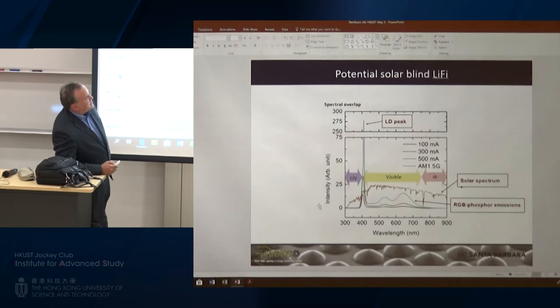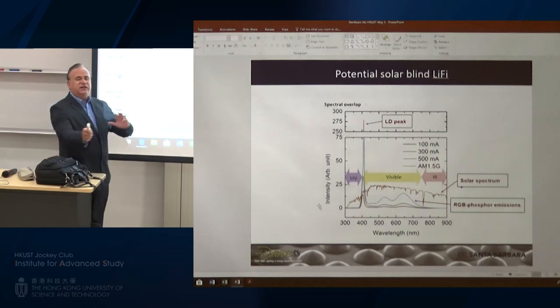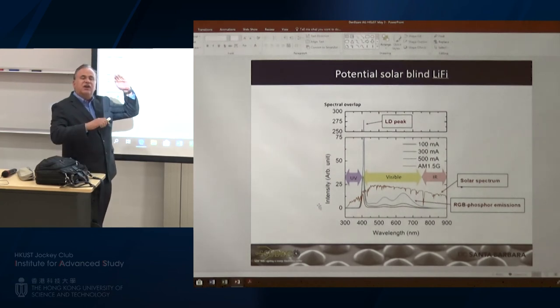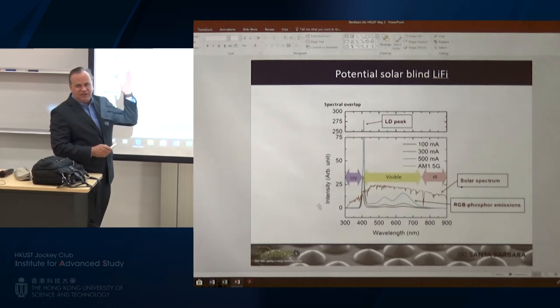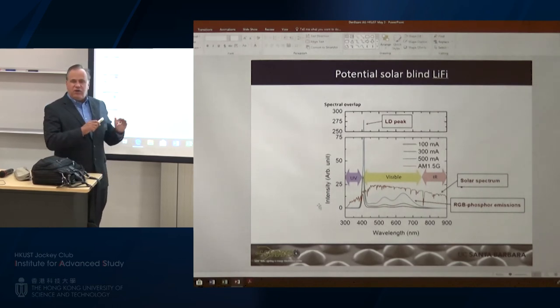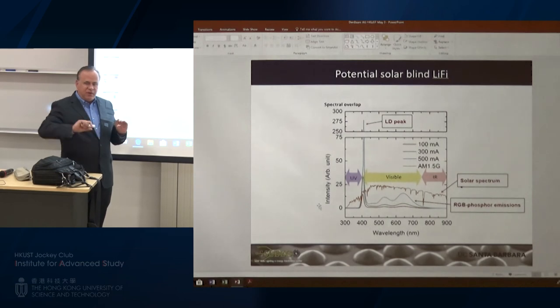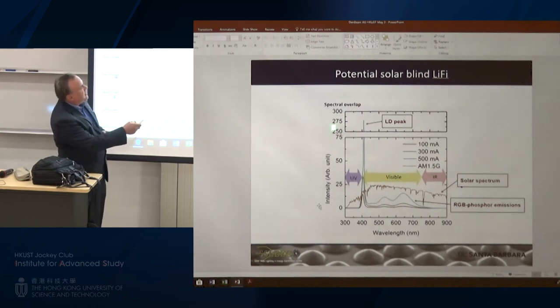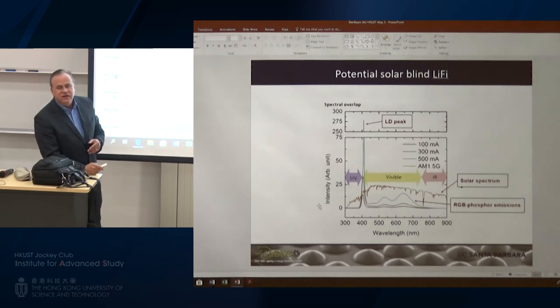Hold on. It's because of this. In the LED, the blue LED light is down here, it's not very high, but in the laser case, you can see that the signal to noise ratio is much higher. That's the main reason. But after you add the phosphor, laser plus phosphor is lower than a pure laser. That's because of the attenuation from the phosphor. Attenuation, okay. The signal to noise ratio just decreases, the power that's coming out. Yeah, it was just the power. If you had normalized it for power, it's the same. Okay. So once you put the phosphor on, this peak dropped. That's all I'm saying. Okay, thank you.